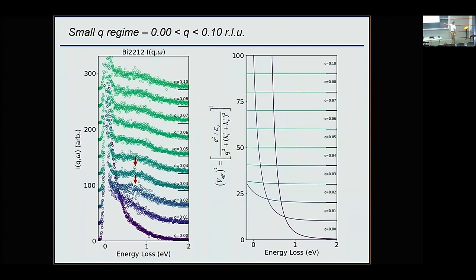At very small momentum, what you see is a funny-looking tail, and then as you increase Q, you see a bump. And the bump is at around an eV, but not exactly, so you might guess that could be related to the plasmon seen in optics. And then at higher Q, it decays into something that looks like just a continuum that's frequency-independent.